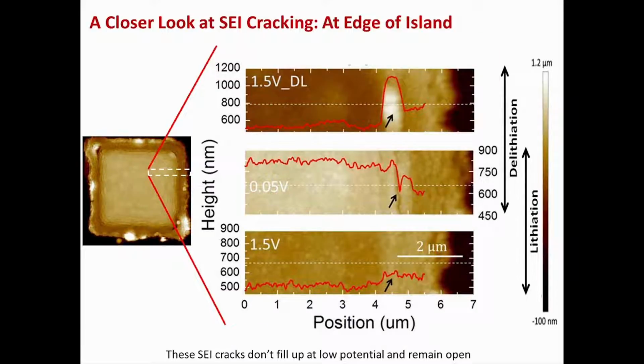If we look at the edge sites, the cracking is less severe compared to the corner sites, because at the corners of these islands, the island is going through almost 3D deformation, so X, Y and Z deformation, but in the edge region it is going through almost 2D deformation. So the deformation is less severe compared to the corner. But you can still see cracking of the SEI layer in this region, and while we delithiate, there is a pile-up of this material, or partial delamination. Again, these cracks don't fill up at these sites.